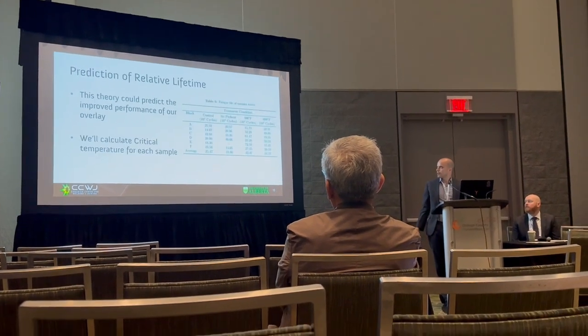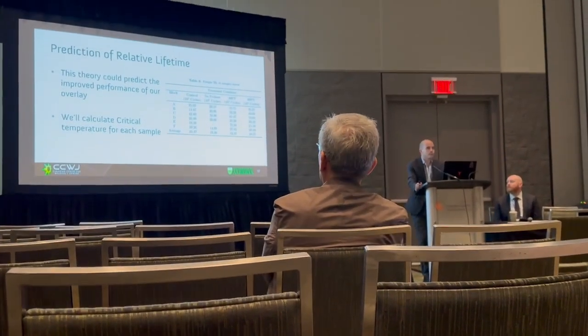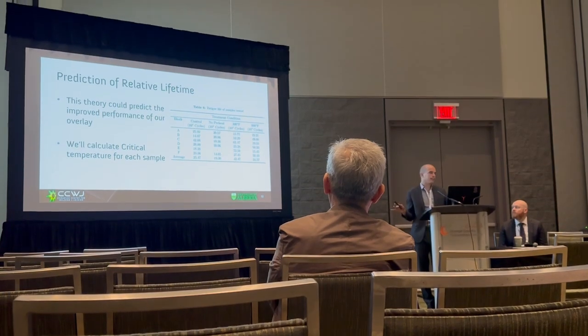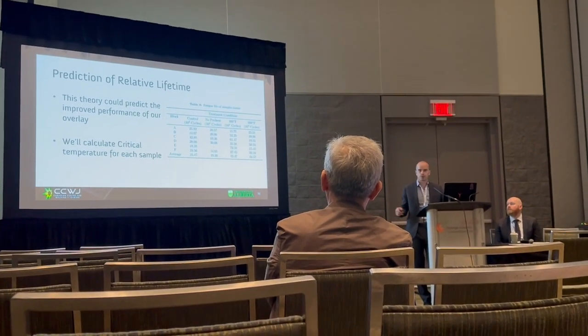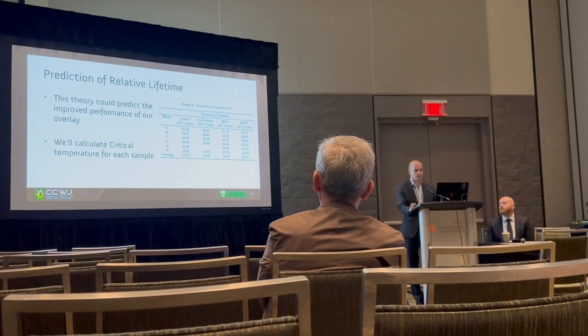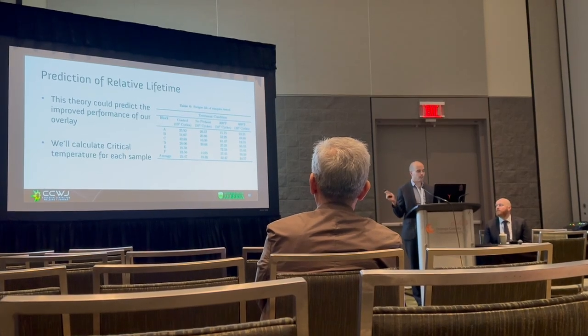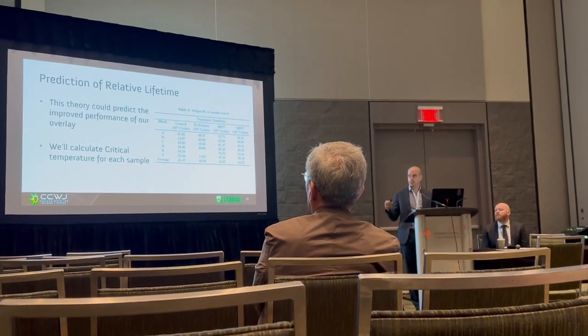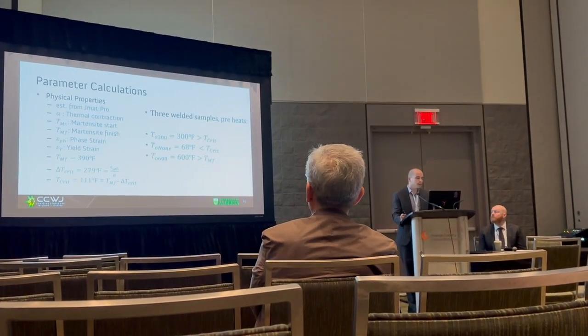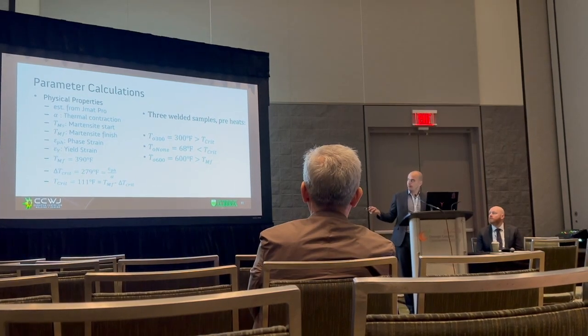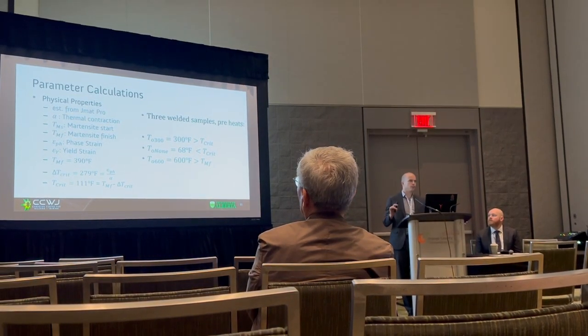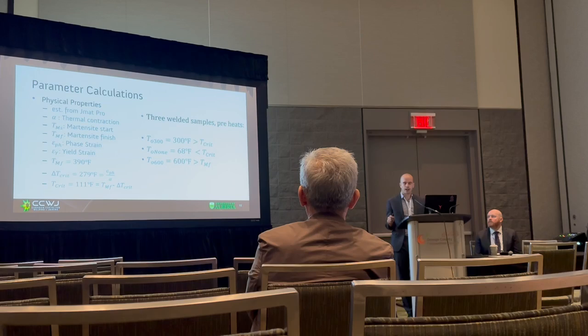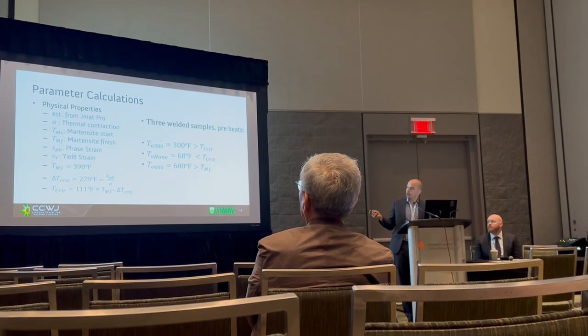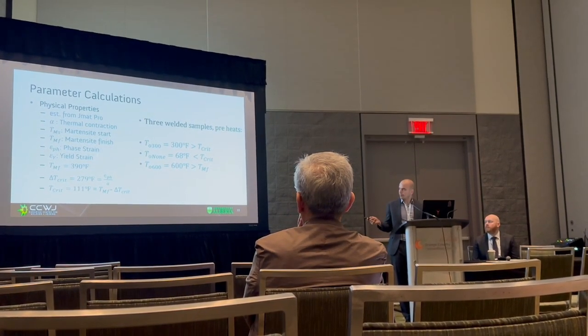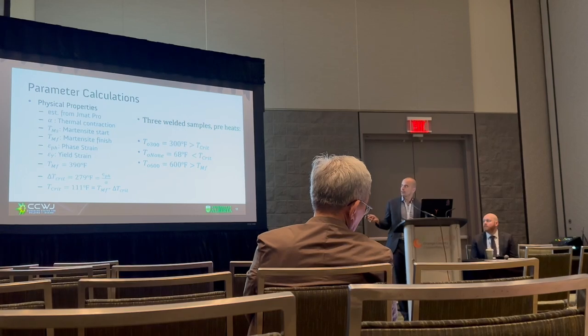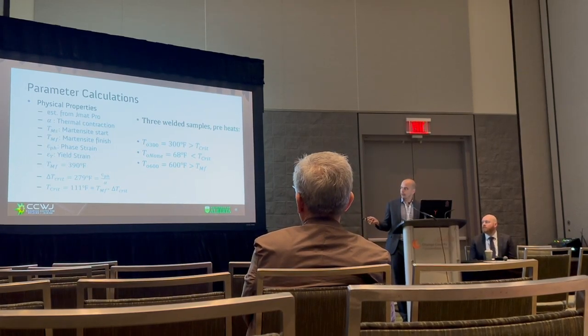So we're going to try to use it. I've got this idea, this is how I think we can control for residual stress, so I think we can predict what these LTT alloys do. We think this was an LTT alloy, we think that's why it exhibited this behavior. Let's see if we can predict it using this model. So I grabbed a whole bunch of properties of that metal they used. Like I said, it was a 13 chrome low alloy steel or high alloy steel. I grabbed all of this out of JMatPro. So there's our martensite finish temperature, the phase strain over the thermal contraction.